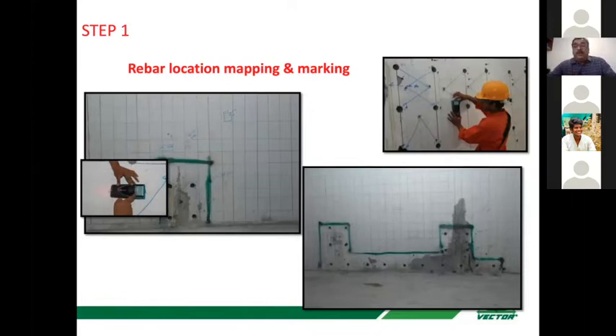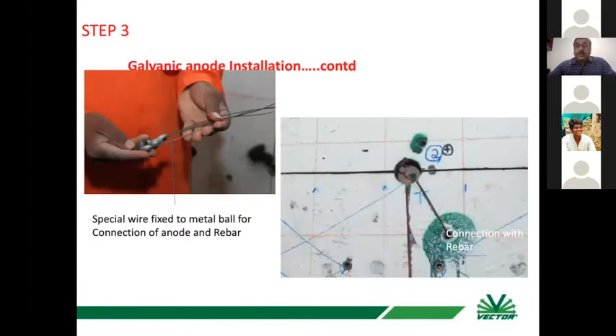Then we found the areas where the half-cell potentials are more negative and the delta is high. And then these are the green lines. And then we drilled the holes between the rebars. So if you see the right-hand side picture, the red lines are the steel and the hole is drilled, and the small hole in the green is the connection with the steel.